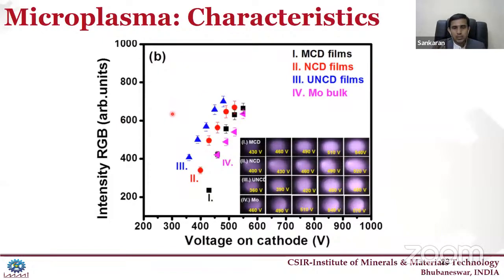We are collecting the plasma images through a USB microscope to our system, and using some software, we are calculating the intensities of the red, green, and blue. So from that, we can also find what intensity is really higher. So you can see that RGB values can be calculated with different diamond thin films here, and the molybdenum bulk, that is also cathode material, we have compared with the diamond. The molybdenum cathode shows very poor plasma emission, yet a higher breakdown voltage, but the others show a very good plasma emission.